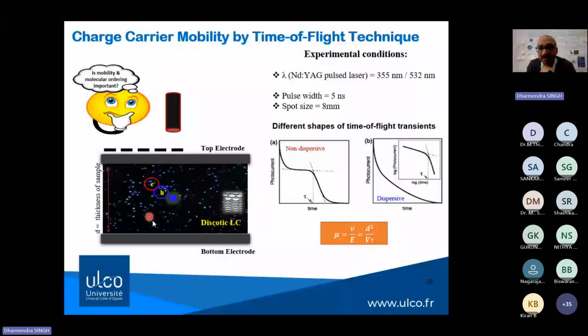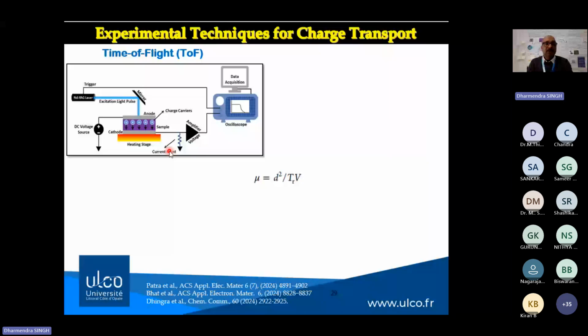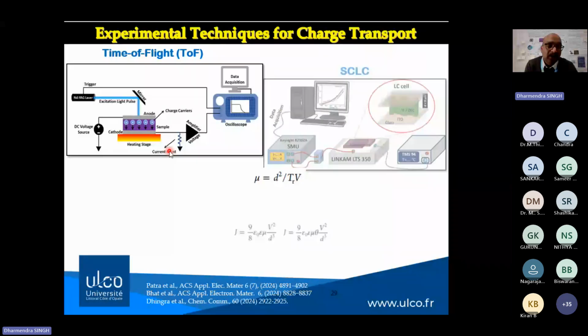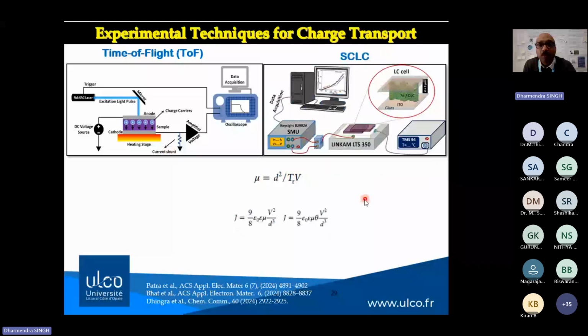So this principle I have already explained, that is the time of flight technique, which is a very nice technique to measure the charge carrier mobility in organic devices. The second technique is the space charge limited current method, in which you have to fabricate a hole only device or electron only device in order to see the current voltage characteristic.